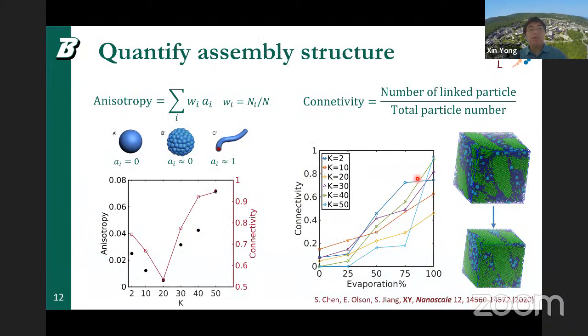So then we further quantify the assembly structure by calculating the relative shape anisotropy, weighted or averaged over the entire system for multiple clusters. Here the relative shape of each cluster represents its general geometry, and then we calculate the average by their weight, which is the number of particles included in this particular cluster over the entire particle number. And then we can see this anisotropic relation is also non-monotonic, with a minimum around 20, which is in agreement with our particle diffusion.